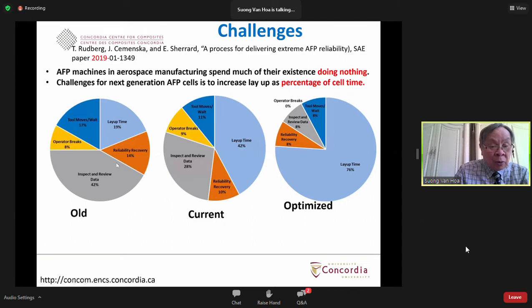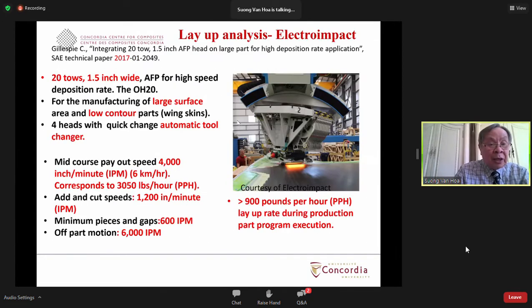Then you also have reliability recovery, 14% of the time. Tool move and wait, 17%, and the Operator Breaks at 8%. So people have improved it with the current technology by 2019. The layup time increased to 42%. Inspect and review goes down to 28%, and the other three aspects remain the same. And then hopefully in the future, they want to improve the layup time to 76%, and the other times remain similar.